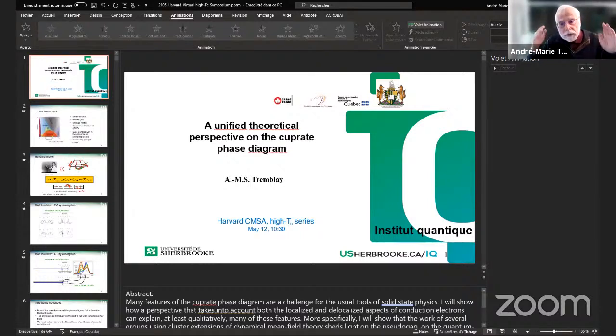And now the superfluid, the superconducting state and everything keeps traces of this normal state. In other words, if you think in renormalization group language, this normal state that I'm describing with the first order transition that's connected to the Mott transition and everything, this ground state is not the true fixed point of the system. But what I'm claiming is that the true fixed point of the system is very close to that. So if you go down in temperature, you're controlled by this normal state fixed point. And then at the last minute, whoops, you go to the other one. And as usual, the long range order phases like superconductivity and antiferromagnetism cure some divergences of the normal state. So here is the same thing. Okay. Thank you.